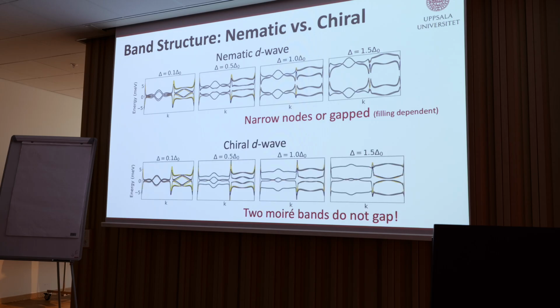The surprise to us came when we plotted exactly the same thing for the chiral state. And as you see, there are states here that never get gapped, states that keep sitting in the gap here. So I have two of the Moiré bands that never gap in the structure. If you saw this and asked which one the material chooses, you would clearly say it's going to choose a nematic state, because the chiral state is stuck with zero energy states. Why the chiral state has zero energy states, we don't fully understand.